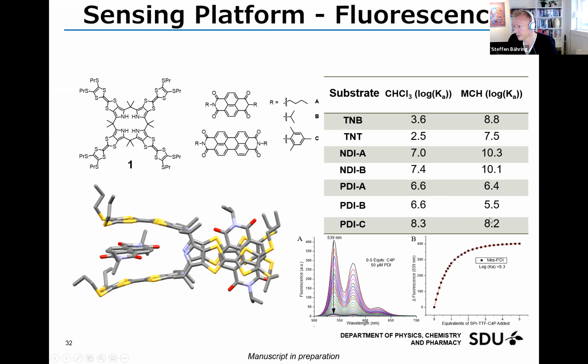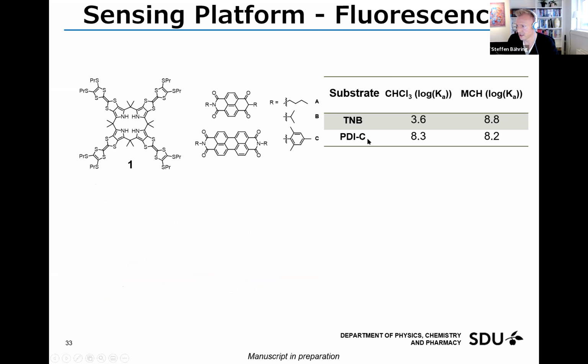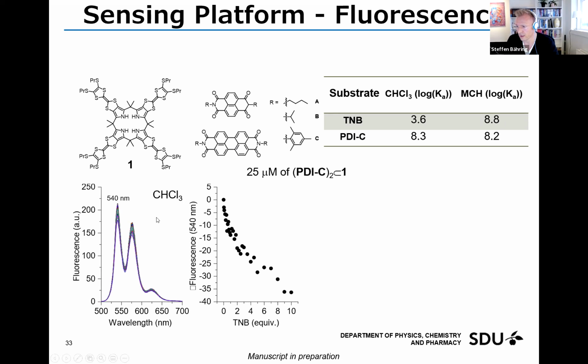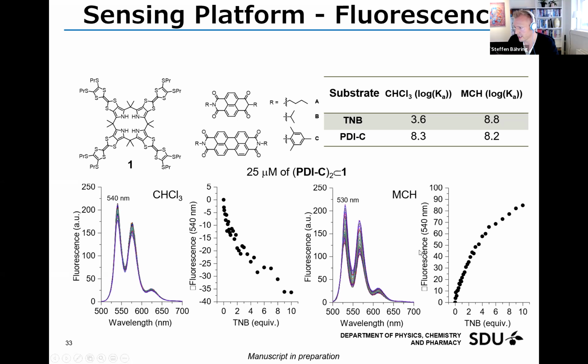So we have this idea that if we use TNB and the mesityl substituted perylene diimide, then we actually have a system where the binding constants are very close to each other, but TNB is slightly favored. So this is our idea, that we want to make an efficient indicator displacement assay using this PDI. And you can see here that if we did the experiment in chloroform, we actually had a fluorescence turn off when we add in the TNB. So it's actually quenching the fluorescence a little bit. But if we make the same experiment in methylcyclohexane, you can see that we have a strong fluorescence increase in comparison. So all of these results are indicative that we were able to make an efficient indicator displacement assay using methylcyclohexane instead.